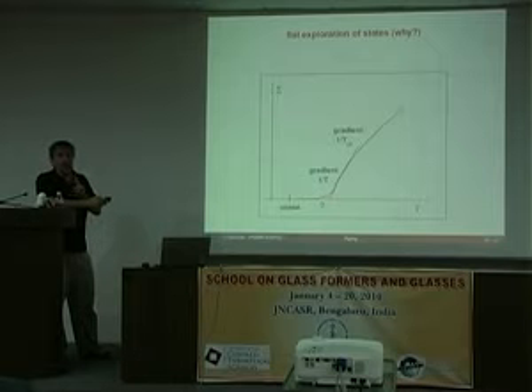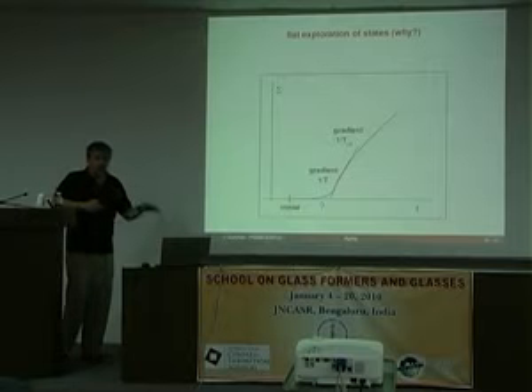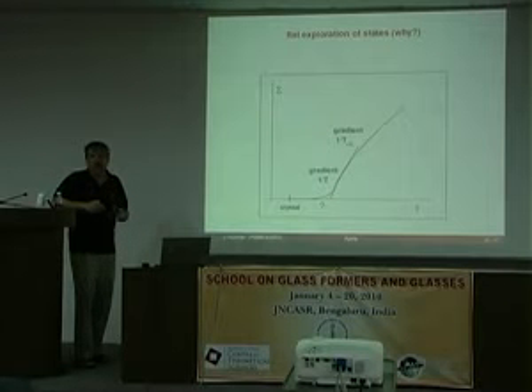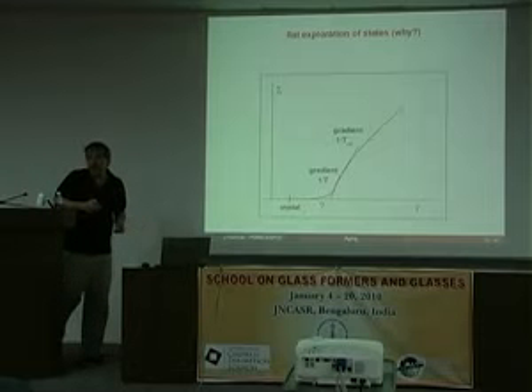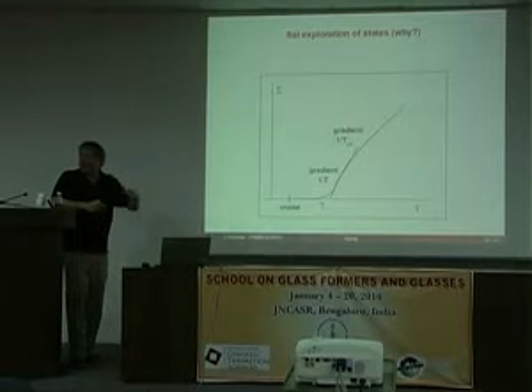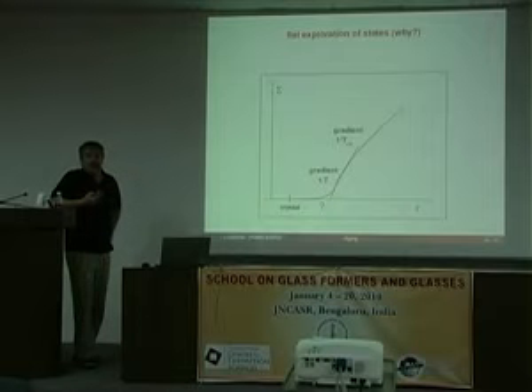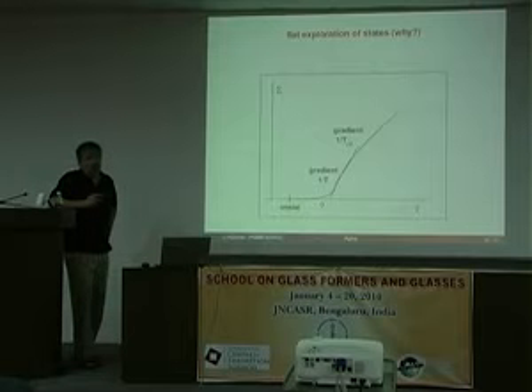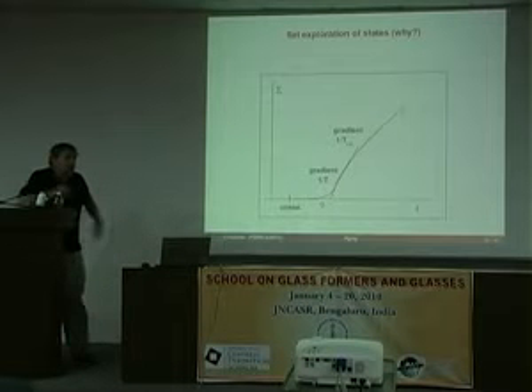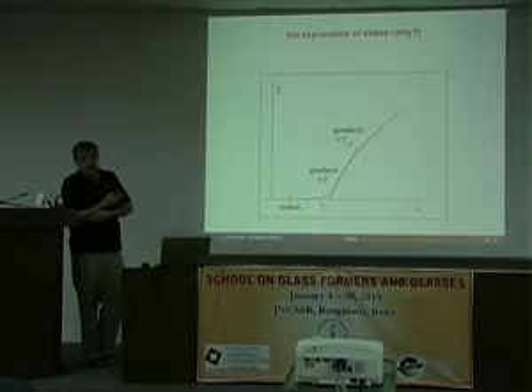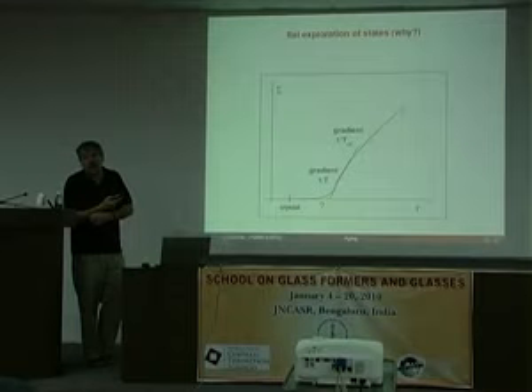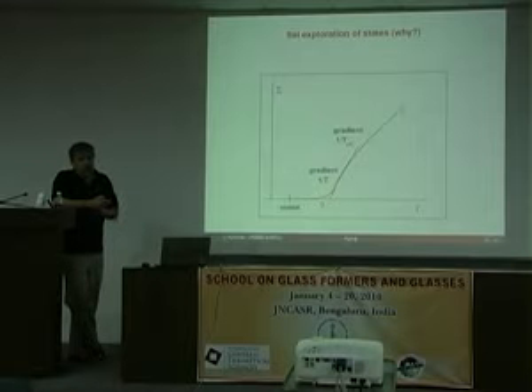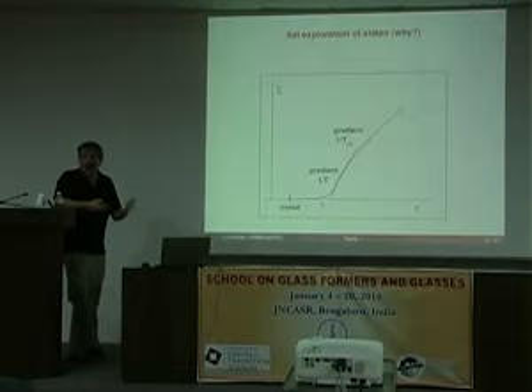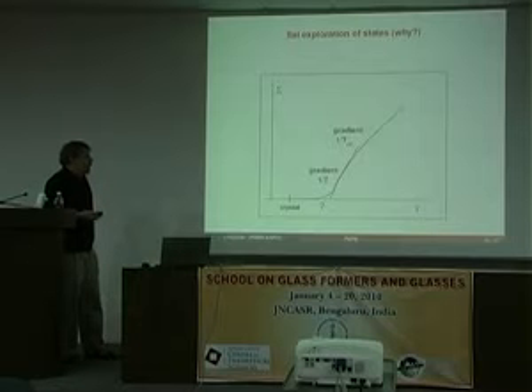At a personal level, I had read Edwards' paper on these flat measures, and like most people, I thought them unreasonable because he was supposing something for which there's no reason on earth why it should happen out of equilibrium, that you have some form of equilibrium-like behavior. But then we realized that what you were observing in these mean field models of glasses was exactly doing this, for no reason that we could understand. And this, in a way, made me, for one, look at the Edwards assumption with much more respect, because at least a model of glass, which is not very far away from a granular system, was doing this. Okay, the model is schematic, whatever you want, but I didn't put this in. It so happens in the solution, for reasons that I believe nobody really understands.